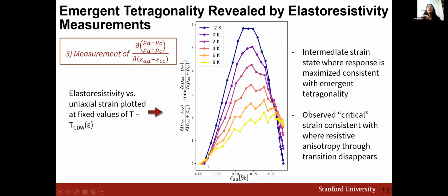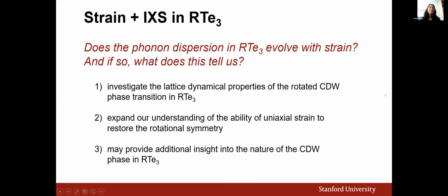So here we have our transverse elastoresistivity, so the anisotropy of the in-plane elastoresistivity plotted as a function of applied strain for a series of different temperatures. And we see indeed there is an intermediate strain state where we see a maximized response consistent with the onset of some fourfold symmetry. And this observed critical strain state is similar to what we saw on the previous slide, where we see this resistive anisotropy disappear.